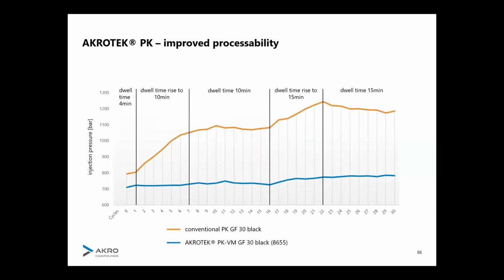So another topic that is often discussed and that reflects a fear of our customers is the cross-linking behavior of polyketone when processed in an injection molding process. What you see on this chart is maybe a bit confusing in the beginning. You see two lines. The blue line is from our AKRO PK grade. The orange line is, let's say, a conventional polyketone. And you see the injection pressure during the injection molding process. We use the injection pressure as an indication for the change of the viscosity, and this reflects the cross-linking